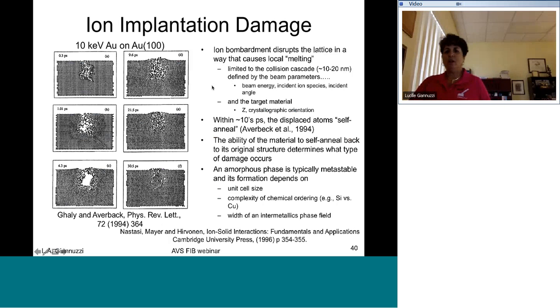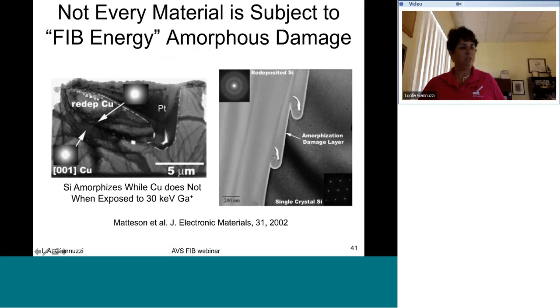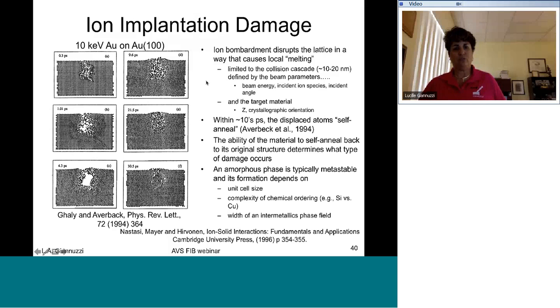So ion bombardment can disrupt the lattice in a way that causes, quote, local melting. And notice this is in quotes, okay, because you're not going to melt a sample. Excuse me, let me go back. So people always ask, what kind of temperature rise am I going to get in my material? And basically, the temperature rise inside of an inorganic material is basically insignificant. Everything is happening at the surface, the top few tens of nanometers. And this happens extremely quickly within just a few tens of picoseconds.